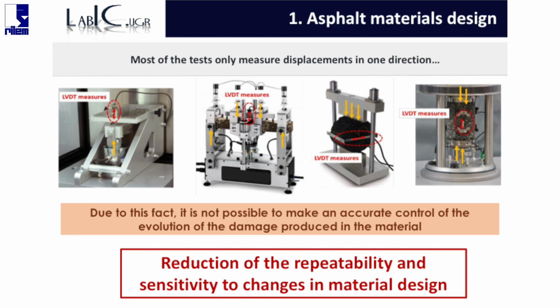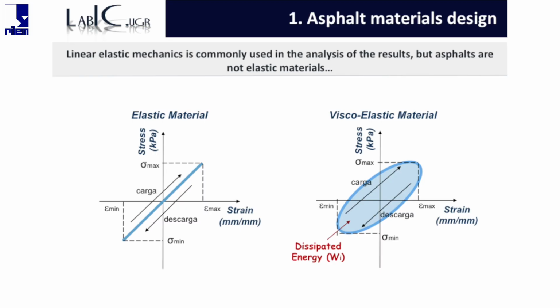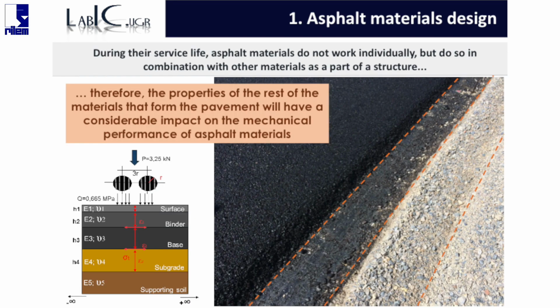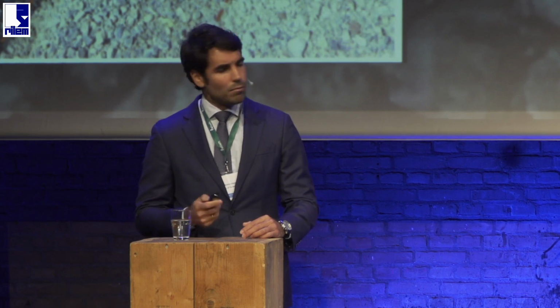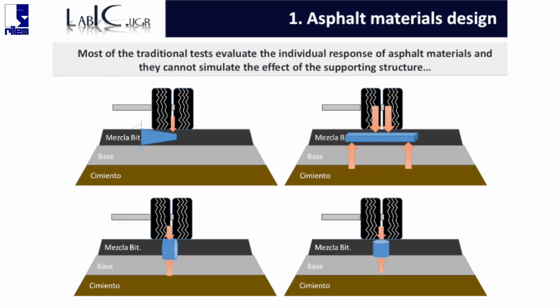Another aspect that prevents us from having an accurate measurement of the propagation of the damage in asphalt material is that most of the analysis of the results use linear elastic mechanics. Asphalt materials are far away from behaving like a linear elastic material. And finally, I noticed that during their service life, asphalt materials do not work individually. They form a part of a complete structure. And the properties of the other materials in the structure have a great influence on the final mechanical response of asphalt material. Most traditional tests evaluate asphalt material as an individual material